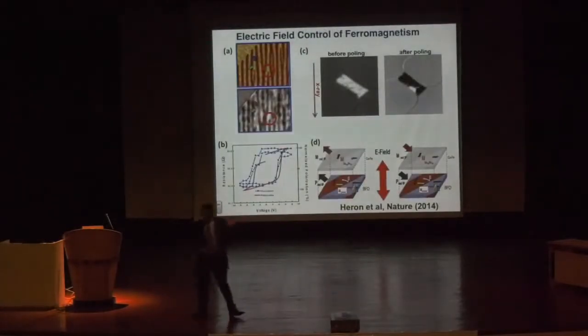What Jorge concluded was that when you do a 180 switch by a single process, it didn't like it very much. In this case, he said it went through these 3 steps, and actually it goes through 2 steps. One, a 71-degree rotation, followed by another 109-degree rotation, adding up to 180. In this case, the canting moment also rotates by 180. That was very consistent with a lot of our experimental data, which is shown in this slide.